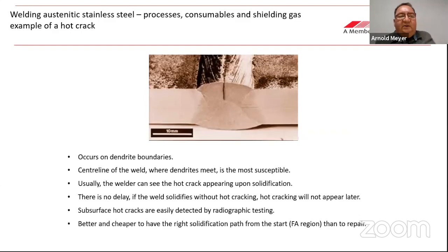Let's look at a typical hot crack. Now, hot cracking takes place on the dendrite or the grain boundaries, right in the middle of your weld, on the center line. That is where all the dendrites get together. Remember that solidification takes place from the sides of the weld, from the cold base metal towards the middle. So right in the middle is actually where those dendrites meet, and that is your most susceptible zone. So usually, not always, but usually, you will see your hot crack appearing in the middle of the weld.